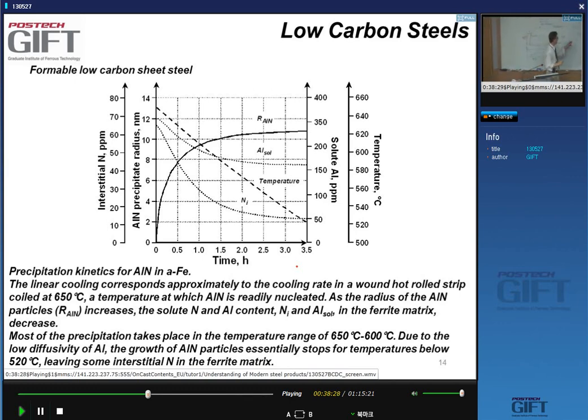Now, this volume here consists of aluminum and nitrogen only. There's no iron here. So this means that to grow, this particle has to absorb aluminum and nitrogen. And the diffusivity of these two elements is very, very different. You know that nitrogen is an interstitial, so the diffusivity of nitrogen is very, very high in comparison to the diffusivity of aluminum. What's more important, and I think I've said this in earlier lectures, is that at around 550, the diffusivity of substitutional elements is so low that you can basically assume that they're not diffusing for all practical purposes. So they stop diffusing.